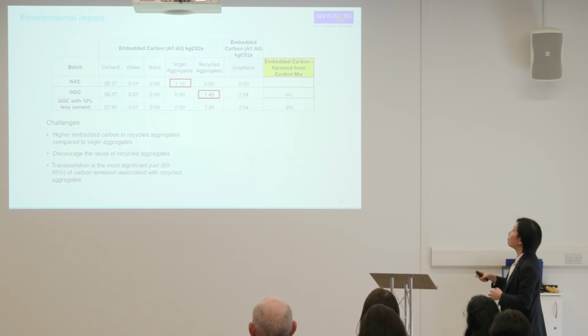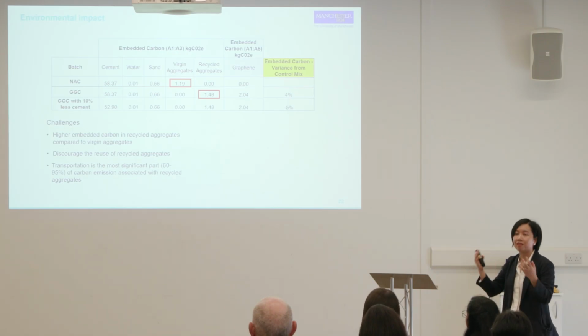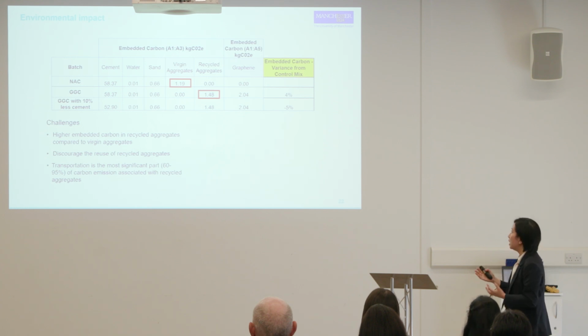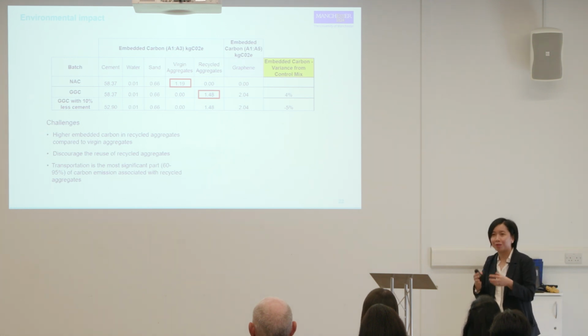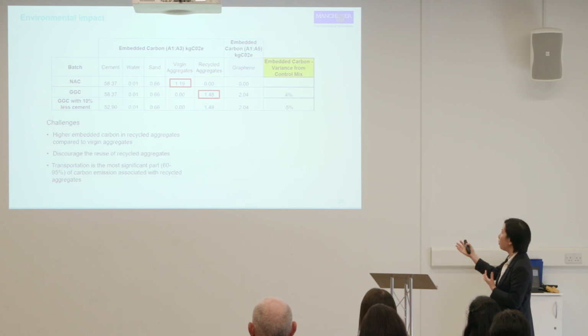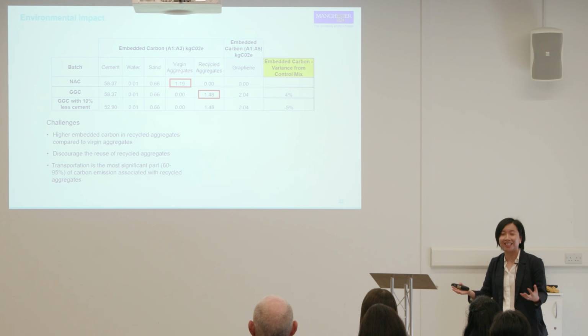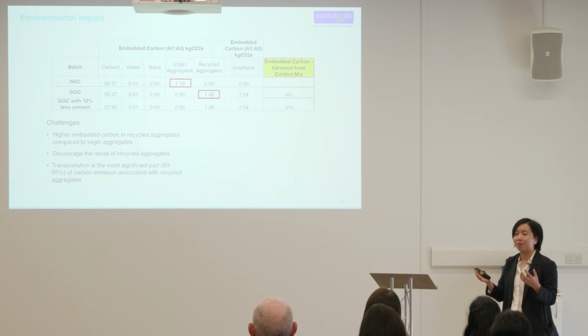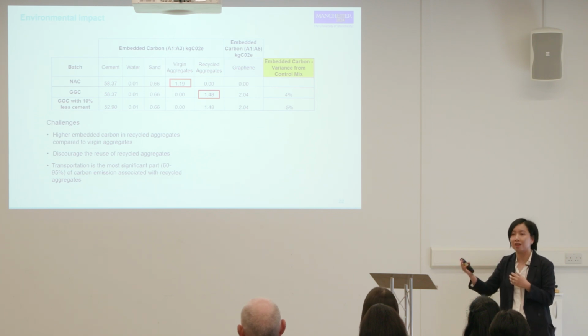And then from the environmental perspective, we've done the analysis for the embodied carbon. When we dug out the raw data for the materials, very surprisingly, we found that the embodied carbon for the recycled aggregates is even higher than the virgin aggregates. The explanation from the literature was that this is associated with the transportation distance between the demolished site and the recycling plants. Agree or not, the data will actually discourage the reuse of recycled aggregates.